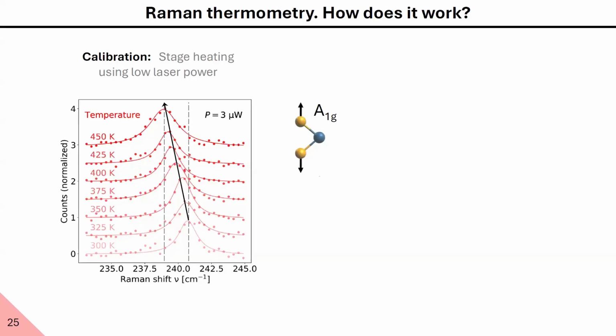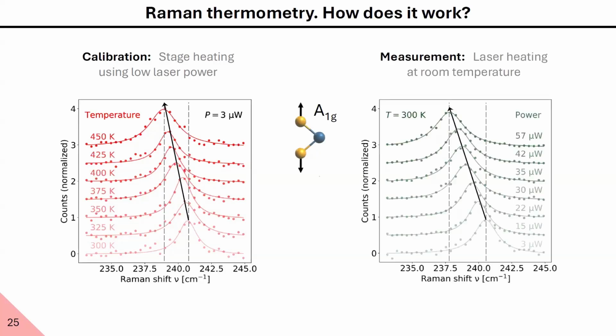our samples. In the second experiment, what we do is to perform laser heating at room temperature. So basically, as we increase the laser power, we have a similar Raman shift. This is a red shifting of our observable just by increasing the laser power, meaning our laser is hitting the sample, and therefore we can correlate the given shift at a given power with a given temperature increase in the sample. And so we have an optical thermometer.